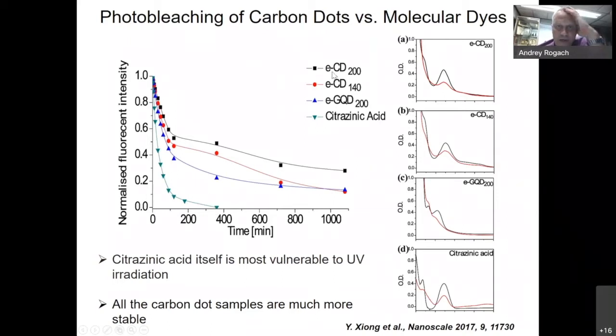And for example, this so-called ECD200, the black dots here, are pretty stable. So the emission still drops, but the remaining emission will stay, and it will stay much longer, actually, which is not the case here. So all the carbon dot samples are much more stable than molecular dyes, which is a good message, right? So we can make sure that these nanoparticles, if we use them as light emitting materials, will be stable against photobleaching.